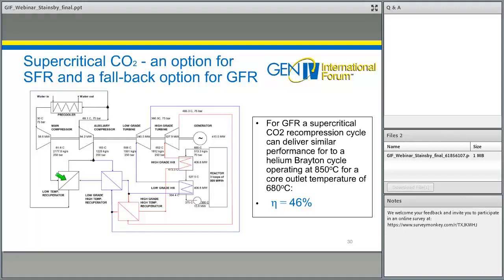One of the biggest problems we have is we have to operate at very high pressure, so we're looking at something like 250 bar for the maximum pressure, which then gives us very thick wall thicknesses for the pipes. It gives us very large temperature and pressure differentials across the recuperators, which present quite significant engineering challenges.